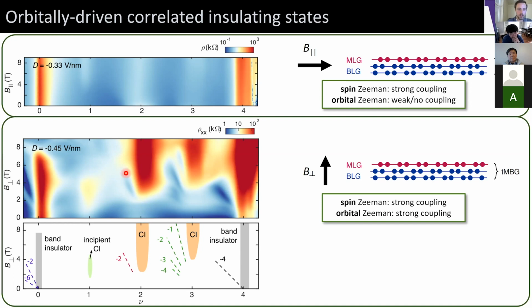At the same time, we see quantum oscillations emerging, starting at high field, but projecting to either half or three-quarters filling, which is suggestive that we're forming new Fermi surfaces as we apply a perpendicular magnetic field. And the perpendicular field should couple strongly to both the spin and the orbital Zeeman terms.